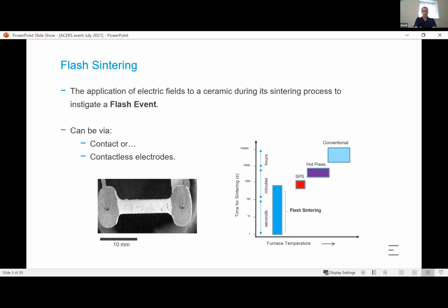Just a bit of a background first then. So if we think of flash sintering as you contact or apply an electric field to a ceramic at a furnace temperature. So that would typically be, say, let's take zirconia as a technical ceramic example. If we apply an electric field at 800 degrees and then apply a voltage across the ceramic, you're getting an increase in conductivity, and then you kind of arrest that power spike and runaway and have a consistent current through it. And that kind of provides a real rapid densification.